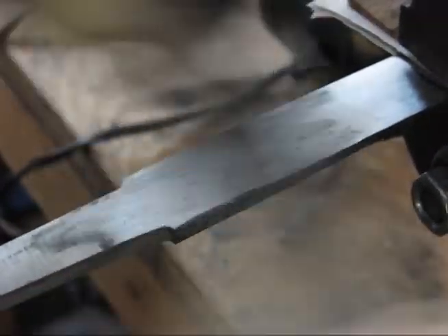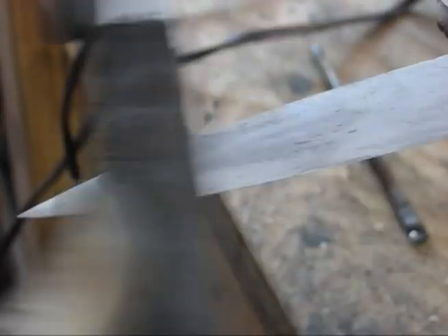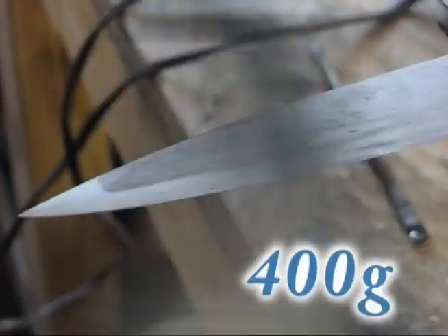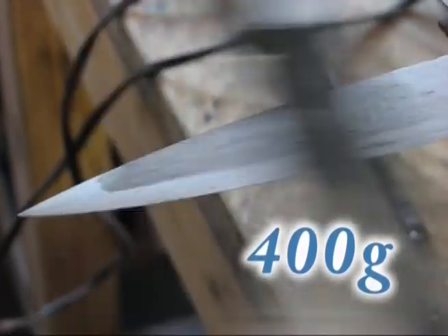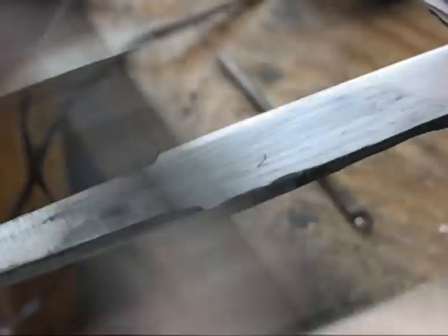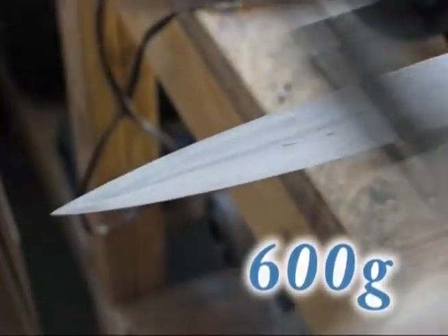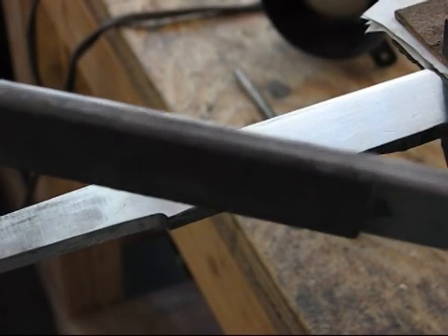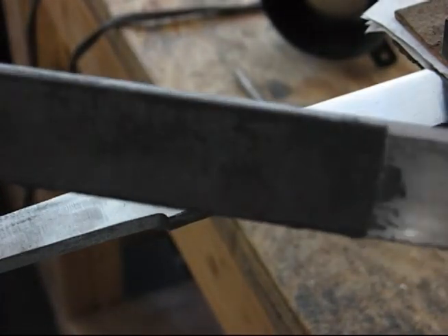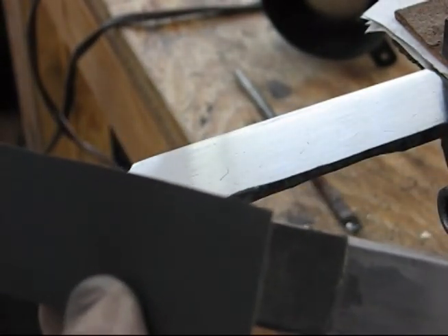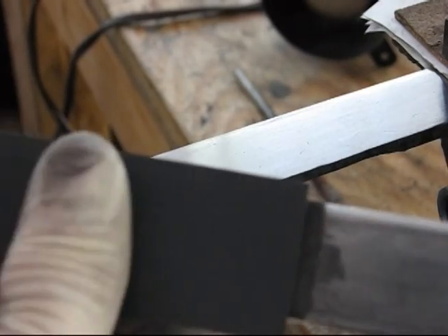Jesus will polish the blade at alternating 90-degree angles to make sure that the marks left by the previous grit are fully visible. His goal is to completely remove the previous marks before moving up to the next grit. As the grit becomes finer, he switches the sanding bar around and attaches the sanding paper to a strip of thick leather glued to the bar. This softer backing helps bring some relief to the blade surface, as it preferentially removes material from the softer layers of metal.